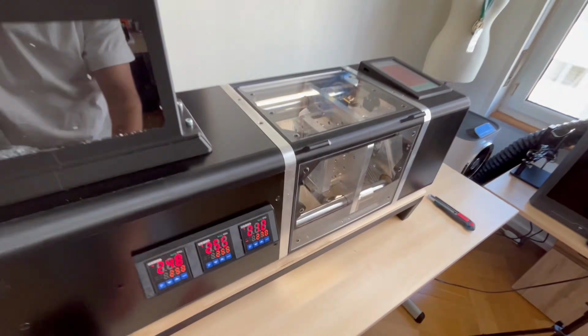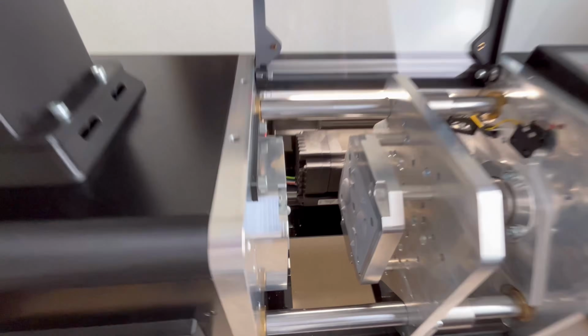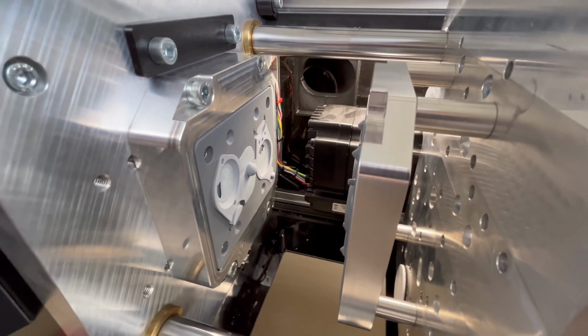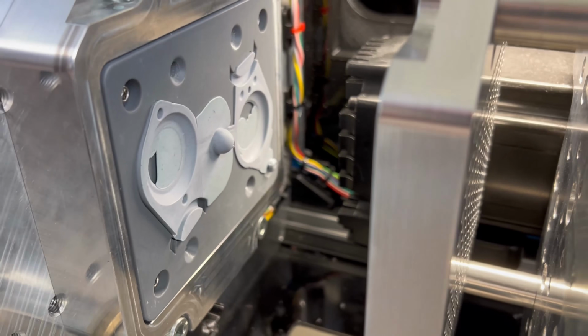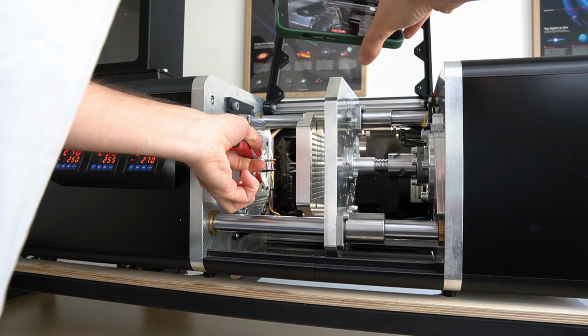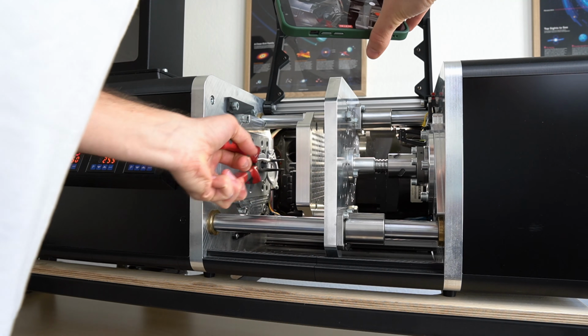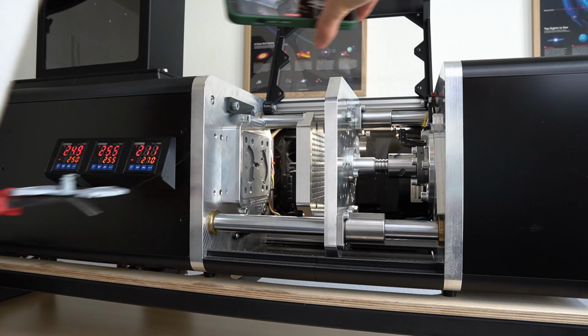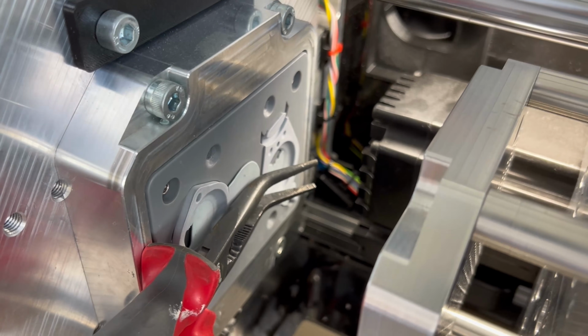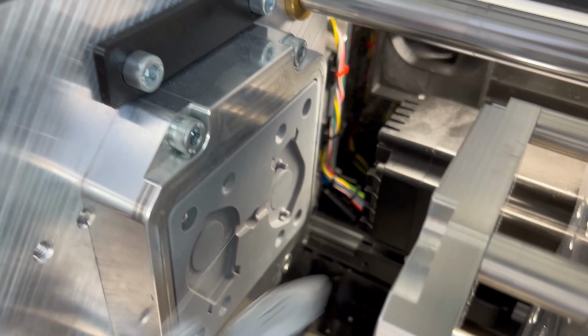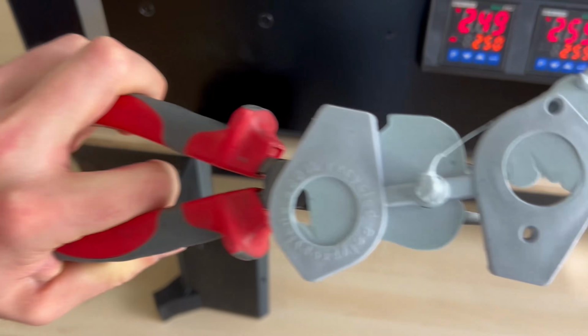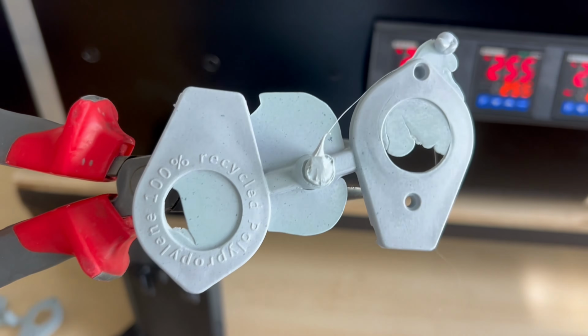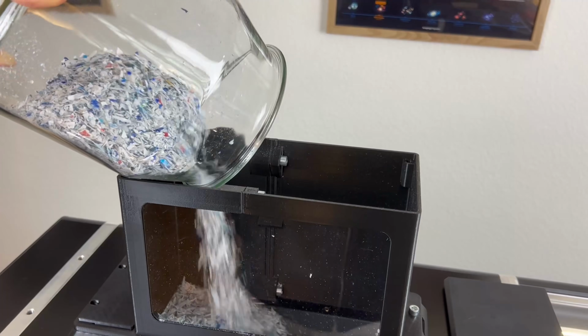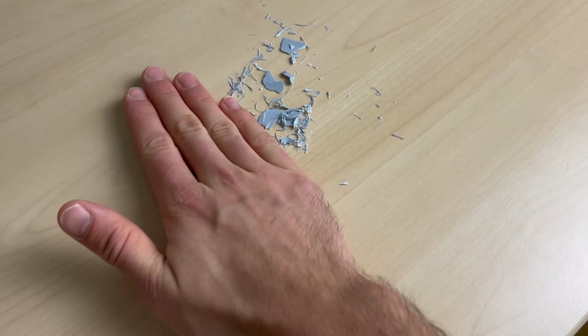Using this inhomogeneous flakes also makes it much harder to predict when the mold is completely filled. As you can see here, sometimes the part is more filled, sometimes it's not filled enough. For me, that is probably the last big thing I need to fix before the machine can run 100% reliably with polypropylene plastic waste. Maybe this could be measured using the motor current sensor or even an in-cavity pressure sensor, or maybe both of them.